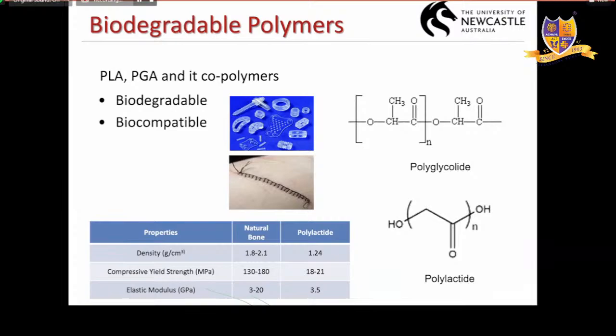But for orthopedic implants, which my group is focusing on, we need a material with high strength. If you compare the mechanical properties of natural bone and this polymer, it's quite low, right? The compressive strength is quite low, and the elastic modulus is on the borderline. So we need a material with better strength, okay? And when talking about strength, out of these classes of materials, I would pick metals. Metals have better strength. You could tailor the properties. You can alloy it. So there's so much you can do with metallic materials.